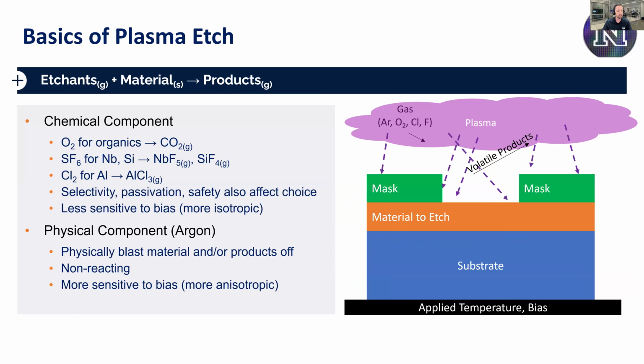It's less sensitive to bias, tends to be a more isotropic, all-directional etch. Physical components, we also can use argon, ionize that in the plasma, and use that to sandblast things off. You can do that with other ions as well, anything that's responsive to an electromagnetic field. However, when we do this, we are not cleanly just removing layers. We're dumping energy into an interface.